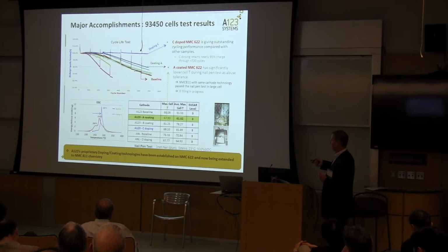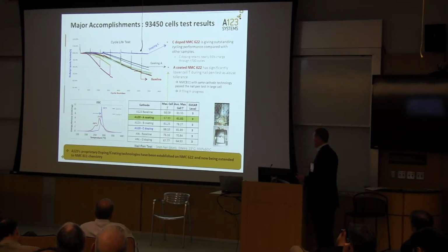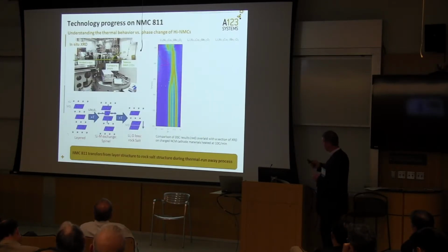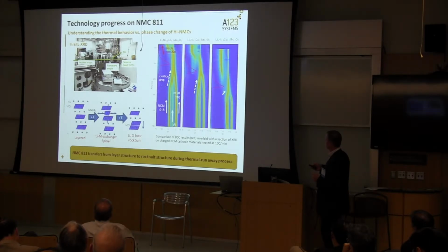So in this case, we're looking at the total energy release or the shift at the onset temperature. This was for a coating for 622, and you can see when we shift this and apply the coating A, we can maintain low EUCAR levels, which is 4 or below is actually passing. And again, this is kind of just what I discussed earlier in terms of utilizing the brain power and the resources at Argonne.